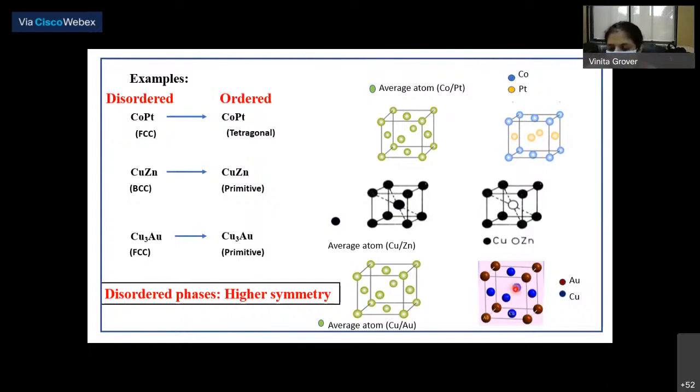You set the lower temperature, record XRD of this material, increase it, record again, and you will observe a similar pattern. When you reach the phase transition temperature, it will convert to this, and suddenly some of the lines in your XRD pattern will disappear. Why? Because FCC has got a lesser number of lines. And that is when you will know that the phase transition has happened. What kind of phase transition is this? It is an order-disorder. A primitive is getting converted to FCC.